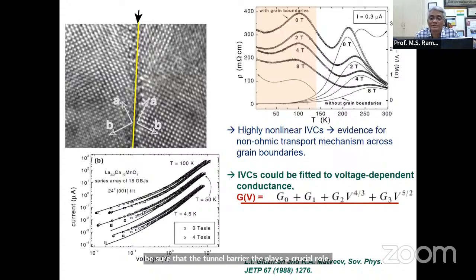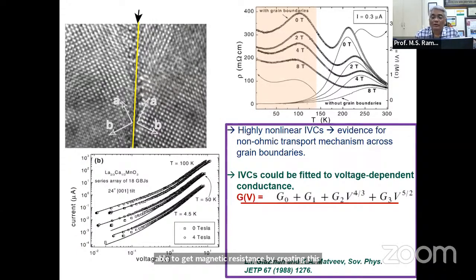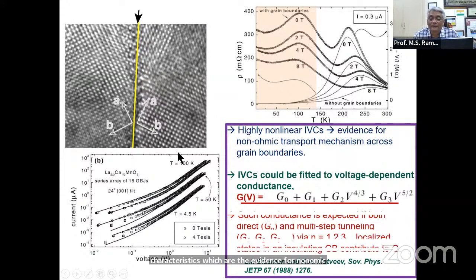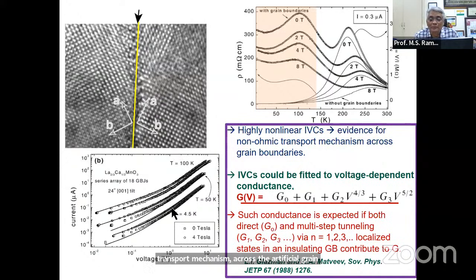And what we showed was one is able to get magnetoresistance by creating these artificial tunnel barriers. But then if you look at the highly nonlinear IV characteristics, which are evidence for non-ohmic transport mechanism across the artificial grain boundary, which is the tunnel barrier, it's very clear from the models proposed by this Russian group long back that the conductance is expected to be largely dependent on the nature of the tunnel barrier.